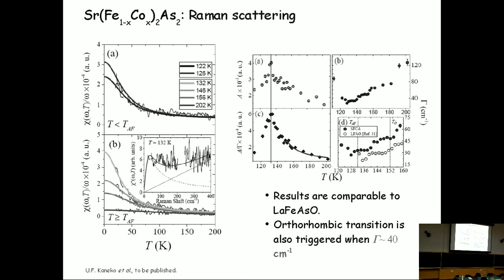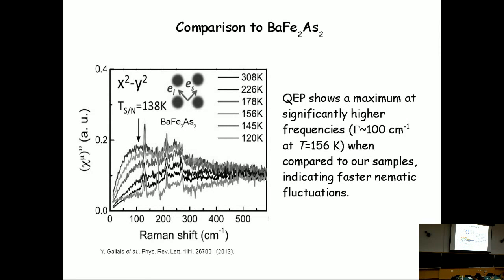And when you do Raman scattering, we basically reproduce the same results that we got for the 1111 system. We have this quasi-elastic peak, this nematic fluctuation peak, whose area keeps going up on cooling up to temperatures close to the magnetic ordering temperatures. And we also see some anomalies in the width of this peak related to the structural phase transition. So again, we don't see the peak at the structural phase transition. We see the peak close to the magnetic phase transition, which is also surprising, but apparently consistent with the other material that we have studied.